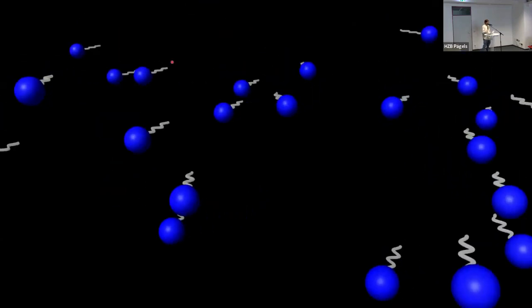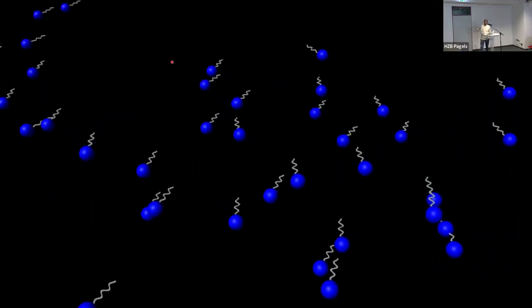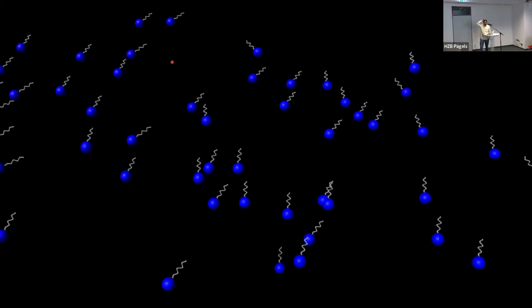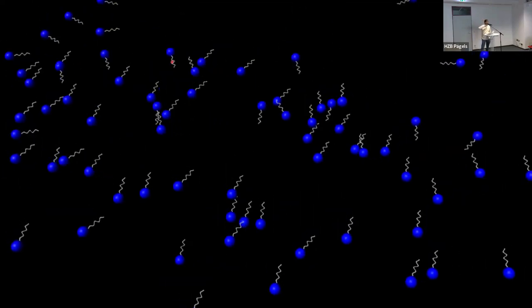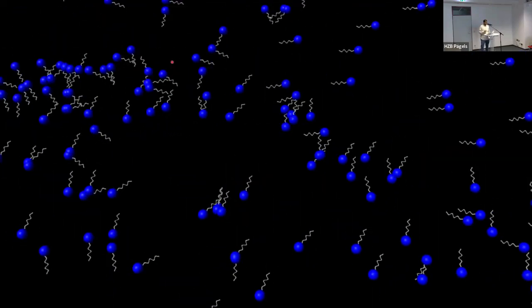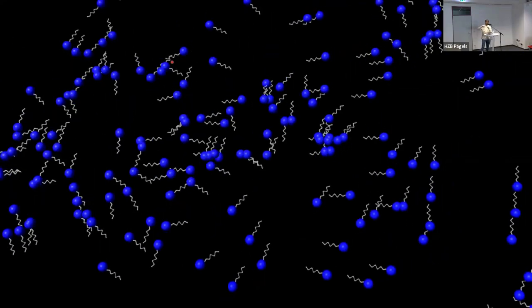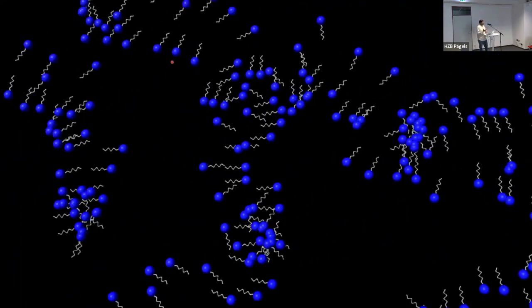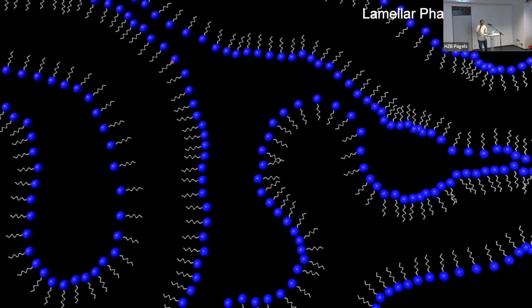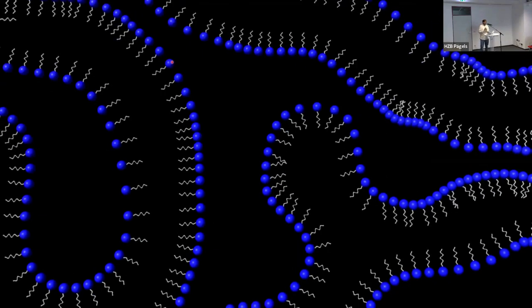So the blue ball is the polar head, and that zigzag is the CH2CH2 hydrocarbon chain, which is non-polar. When you add them into the solvent, which is a xylene and water mixture of polar and non-polar, they try to form micelles. But the concentration is such that they form these lamellar phases.